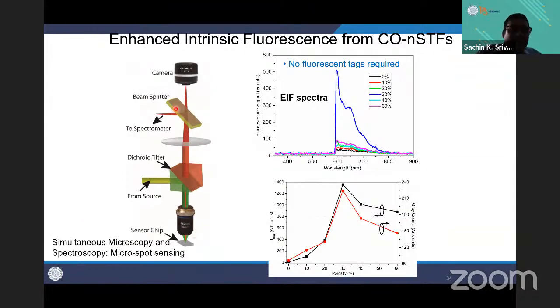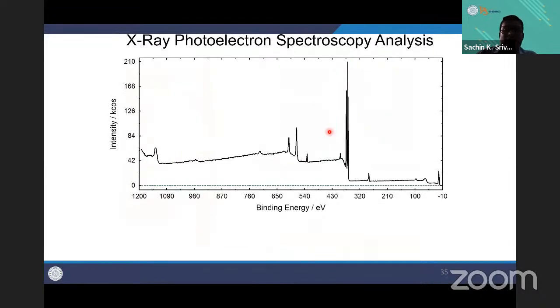What I am doing is that I made a custom setup where light is coming from this side, and I put my sensor chip here, and from the same setup I am using it for the camera and I am sending the signal to the spectrometer. So from the same micro spot I am doing microscopy and spectroscopy. Here you can see that I am getting the enhanced fluorescence signal from this surface, and at about 30% porosity I am getting enhanced signal. So I am using this as the optimum film.